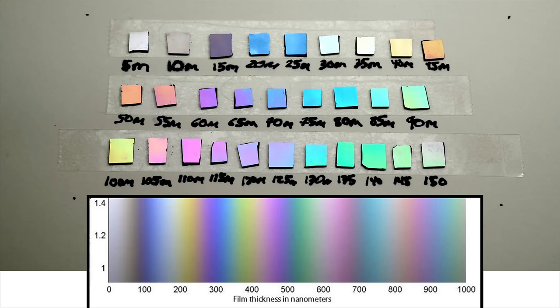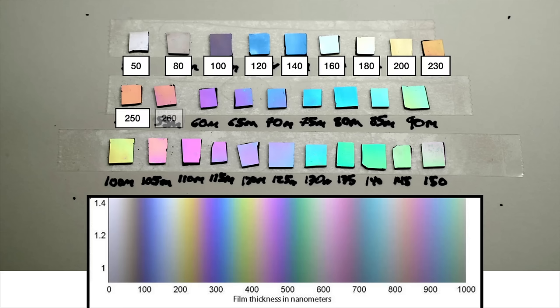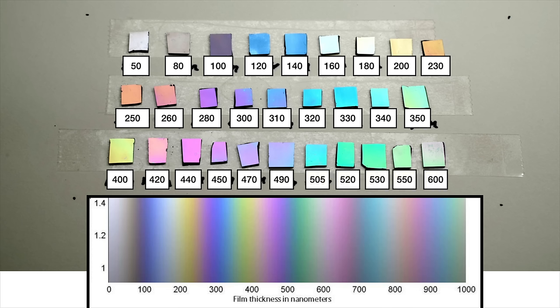Armed with this knowledge, we can use this chart to estimate the thickness of our various oxide layers. I went ahead and labeled all of the chips with my best guess from the chart. If we're careful, we can expect our estimates to be maybe 25 nanometers away from the actual value, which I would say is a pretty good accuracy given that we're measuring nanometers with our eyes. Also, for the kind of stuff we're hoping to create, plus or minus 25 nanometers should be decent.